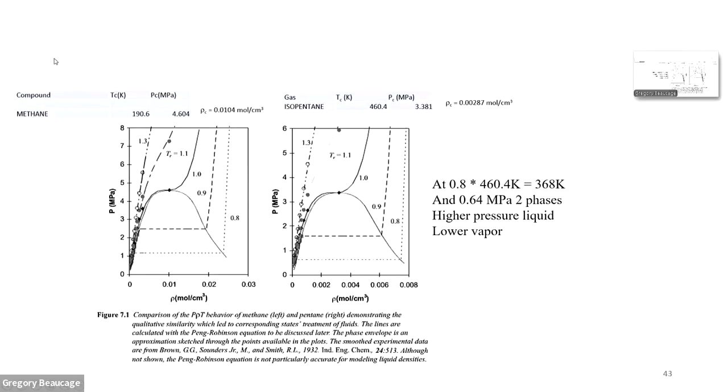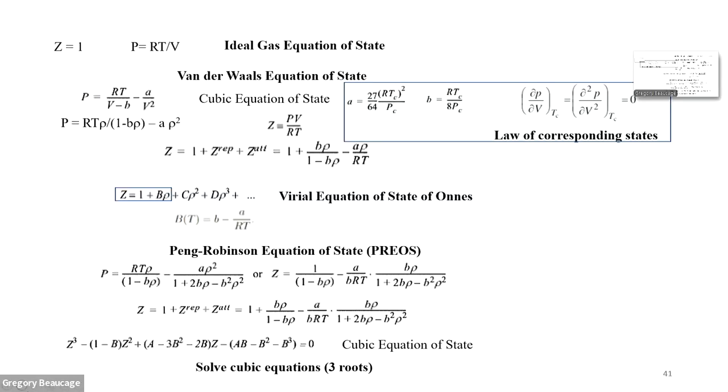And the simplest one is the van der Waals. Then you can get more and more complicated ones depending on what you want to put into this. You can add other parameters other than A and B, like the acentric factor or a polarity factor. People just keep piling on other factors into these equations of state that make them so complicated you have no idea what they're talking about, but they're written for one particular material. The most general is van der Waals, and the most useful is Peng-Robinson. There are others you can use if you're kind of desperate, for different things.